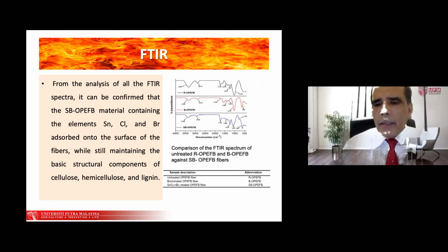And we also analyzed the untreated oil palm fiber, the brominated, and the brominated with tin chloride, and from the FTIR analysis, all the spectra confirmed that the SB material, which has both bromine and tin chloride treatment, contains those elements. We found that the SnCl and bromine are adsorbed onto the surface of the fibers, while still maintaining the basic structural components of cellulose, hemicellulose, and lignin. So treating these fibers did not disturb their structure.